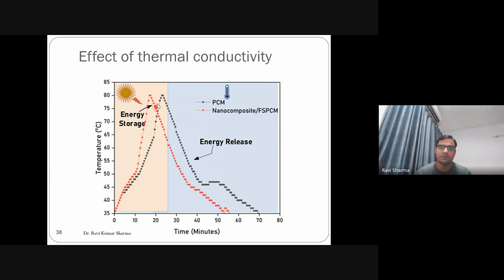The red line goes up and then comes down, so it makes a mountain. That means, let's say, it starts with a temperature of 35 degrees centigrade. It's a material's line, basically a pure PCM. The PCM starts getting heated up till this point, and let's say this is the charging time, meaning the melting period, and then this is the solidifying period. So one complete melting and one complete freezing takes approximately 70 minutes, from 0 to 70 minutes in the case of PCM, following the black line. So a pure organic PCM is roughly taking 70 minutes for one heating and cooling cycle.